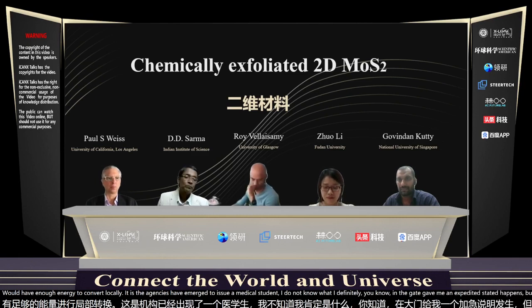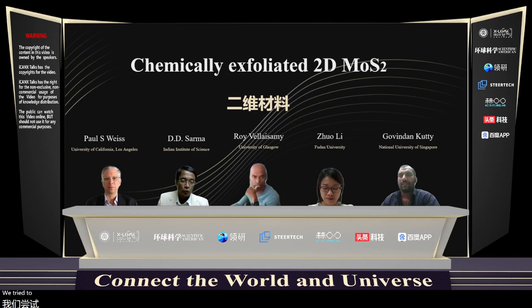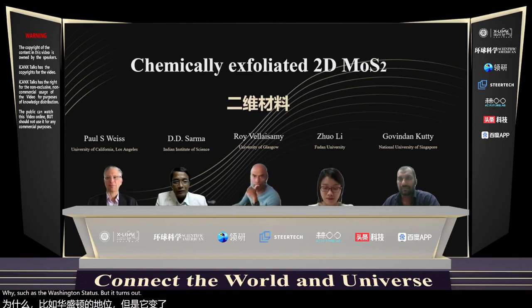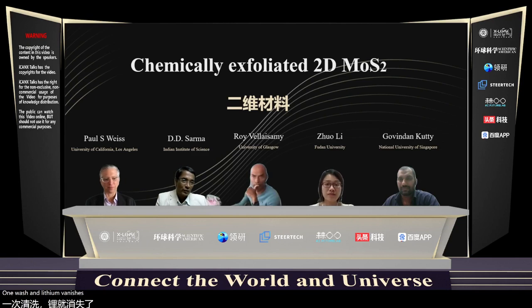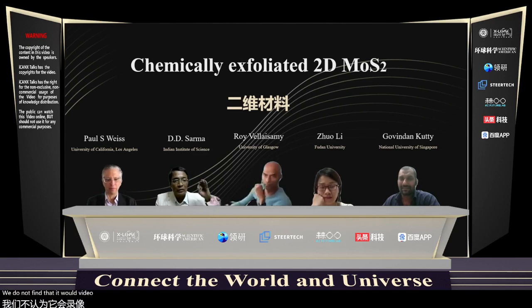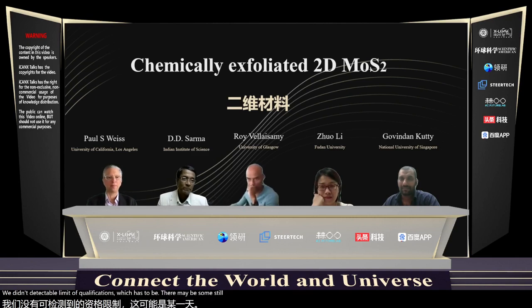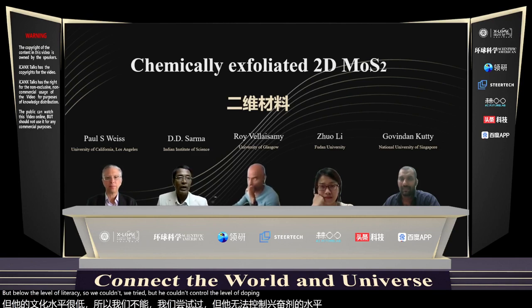We tried to control the lithium doping by successive washing stages, but it turns out that with one wash, lithium vanishes because we wash it with water. After one wash, we do not find any more lithium within the detectable limit of our photoelectron spectroscopy. There may be some still remaining, but below the level of detection. So we tried, but we couldn't control the level of doping by that method. Okay.